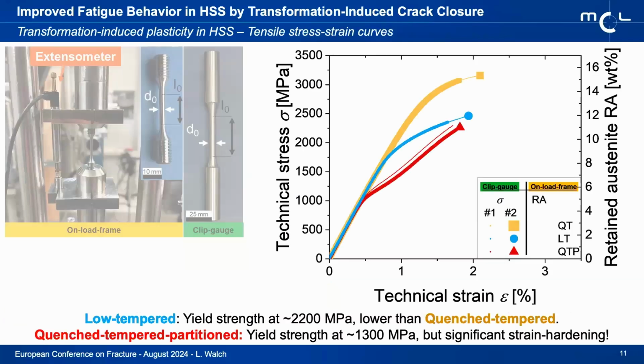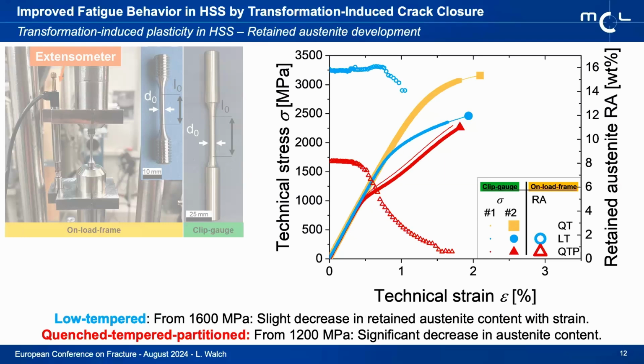Looking at the stress-strain curves, we see that a lot has already changed and happened in one high-speed steel grade just by retaining a bit of austenite. Mostly, of course, the ultimate tensile strength is lowered, but what's also pretty evident is that this transformation strengthening effect occurs in the quenched and partitioned material state until a similar ultimate tensile strength as with the low tempered material state. If we add also the retained austenite contents that we got from monitoring at DESY, you can see that this agrees quite nicely with our stress-strain curves, and we can also see that the retained austenite content decreases below the reasonable detection limit of 2% until failure of the specimen occurs.